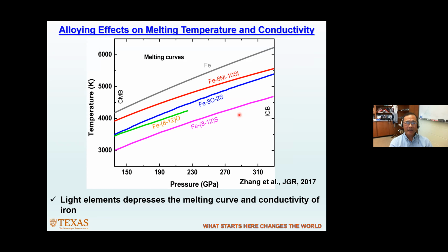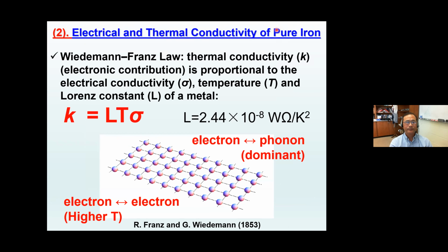So once you actually add light elements, there's melting point depression. So basically the melting temperature of iron decreases depending on the amount and the light elements that you use. So this melting point depression can be as large as about 1,000 degrees. And similarly, if you add light elements as impurity into the iron, the conductivity would actually drop.